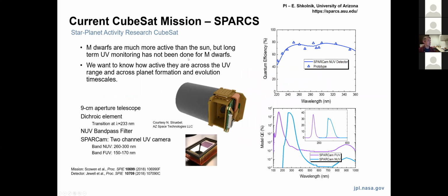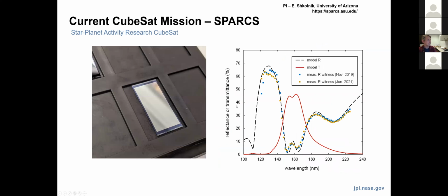We have developed coatings for a CubeSat mission called Sparks, which is led out of University of Arizona by Evgeny Shkolnik. This is a 2-channel instrument which operates with a conventional standalone filter in the near UV, but again, we couldn't find a far UV commercial filter that could operate with high efficiency. And so we've opted to, again, use this integrated metal dielectric filter to produce a response that can even exceed the peak efficiency of the near UV channel in this case. Here's one of the detectors developed for Sparks and some of the characterization data that was done on witness samples.